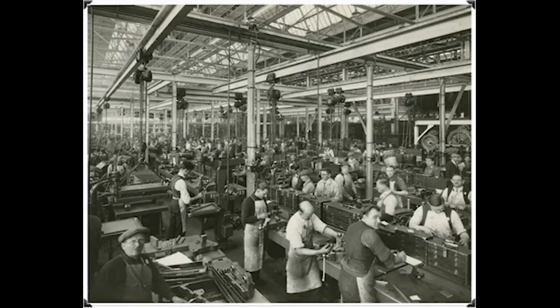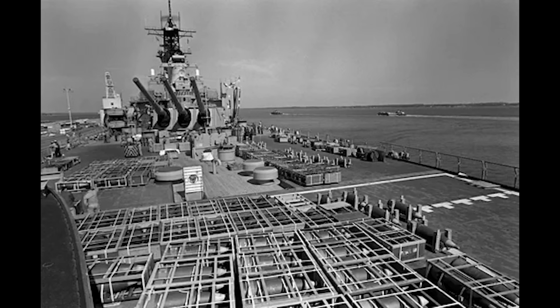Instead of cementation, Midvale used only differential hardening, but with an immensely thick hardened layer, extending to approximately 80% of the distance from front surface to back surface. This super thick face, combined with what turned out to be a fortuitous optimization of the tempering temperature that Midvale had discovered almost accidentally through trial and error, created armor with unprecedented ability to shatter projectiles.